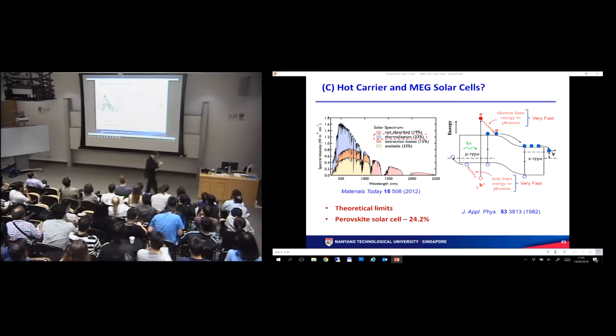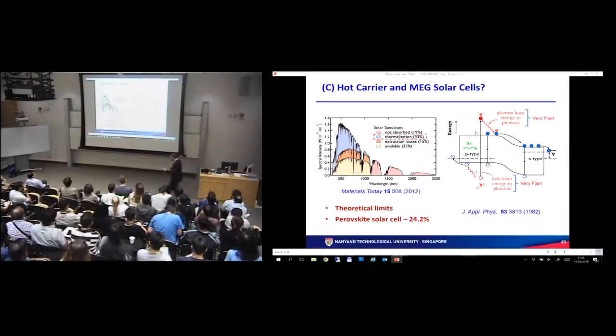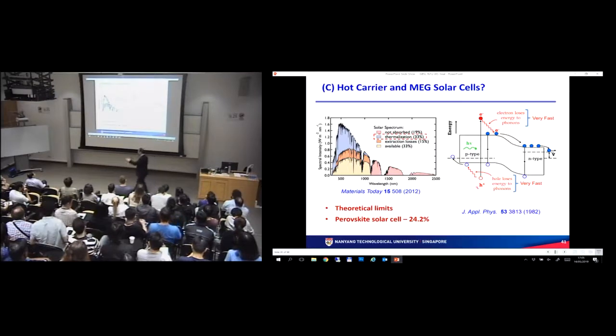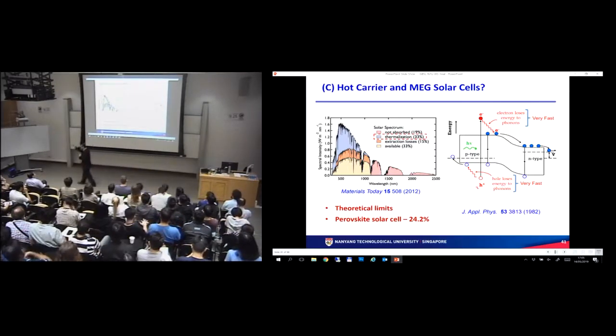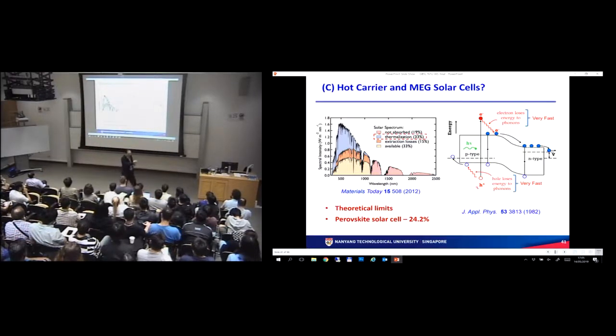Now, look at the semiconductor material. If the semiconductor absorbs a photon that has an energy larger than the band gap, it creates an electron and hole pair high above the band gap. Now, this electron and hole pair has a lot of energy. They are termed hot carriers. These hot carriers will lose their excess energy very quickly to the lattice, to the phonons, in a very short period of time, typically around 100 femtoseconds.